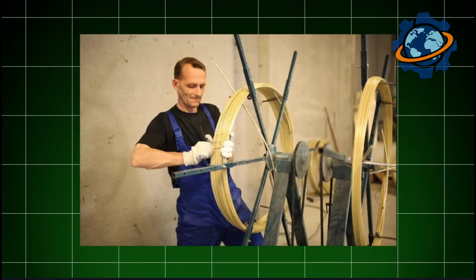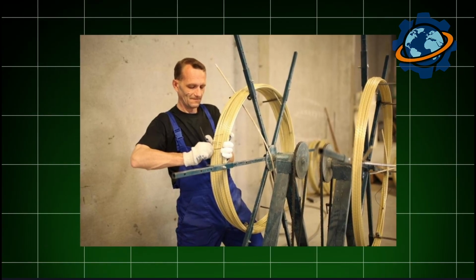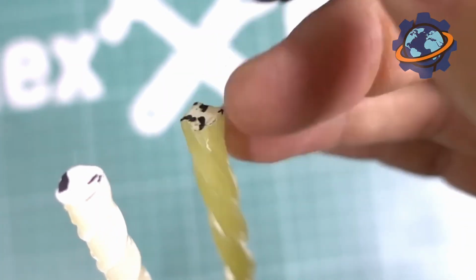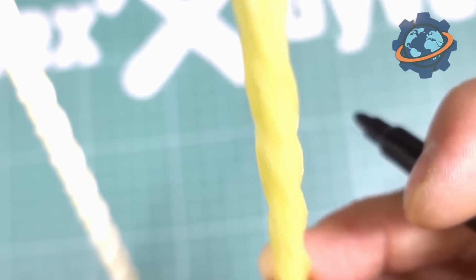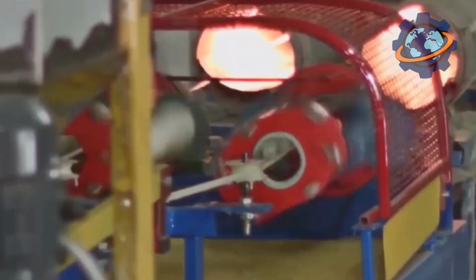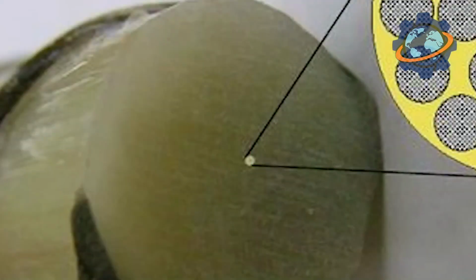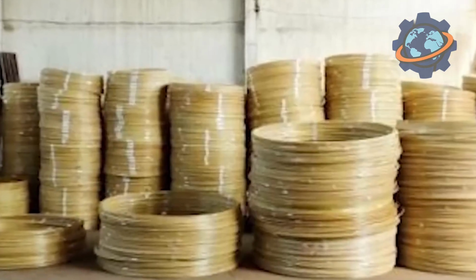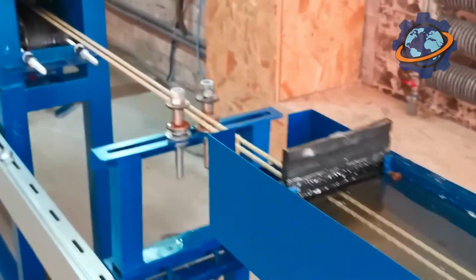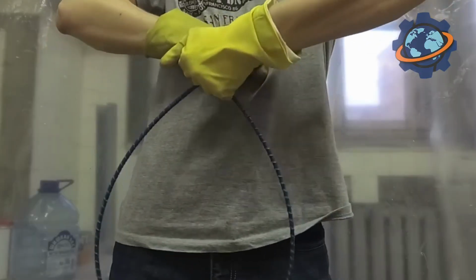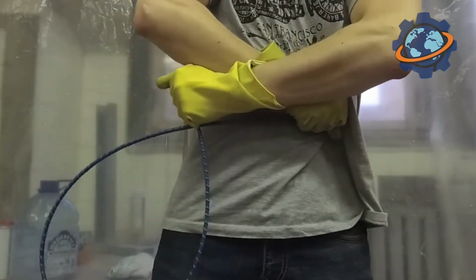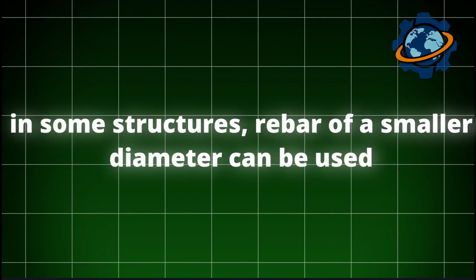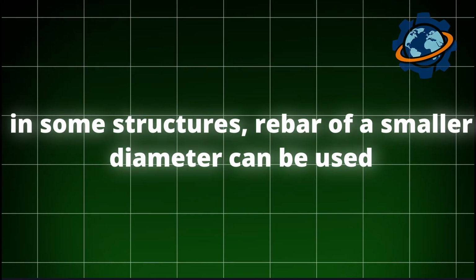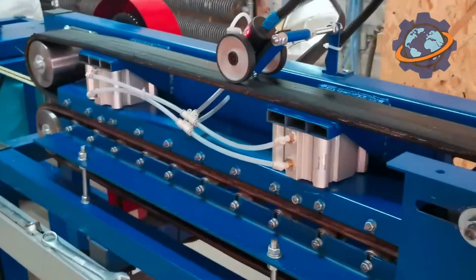On the site itself, 2 workers can easily carry whole coils or bundles of fiberglass rods, whereas moving steel requires a crane. This is a colossal saving in logistics and labor. Second is strength. And here, fiberglass just steps into the ring and knocks out steel in the first round. Its tensile strength is about twice as high as that of standard steel rebar. So you understand, to break a fiberglass rod, you need to apply twice as much effort as for a steel one of the same diameter. This means that in some structures, rebar of a smaller diameter can be used, saving even more weight and volume.